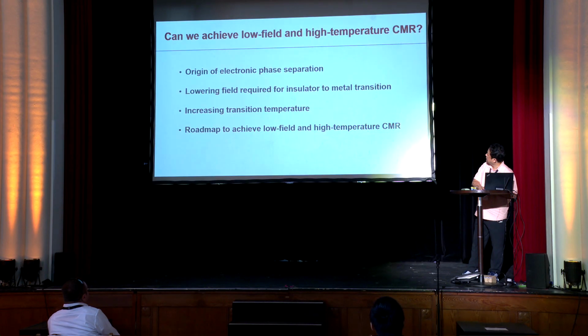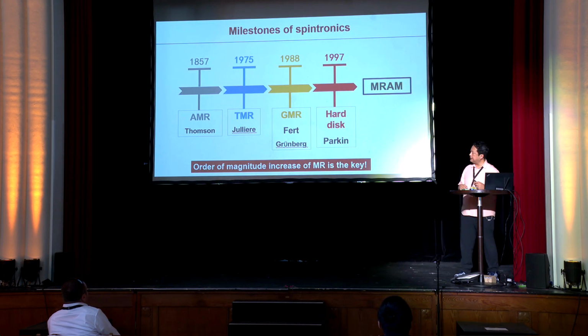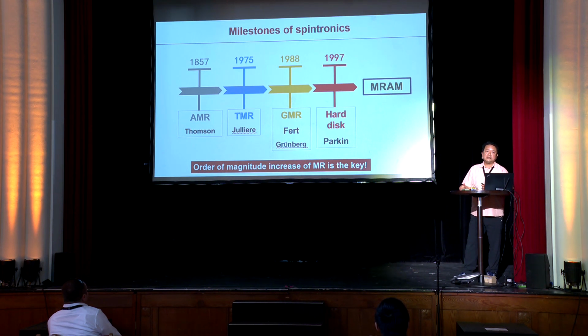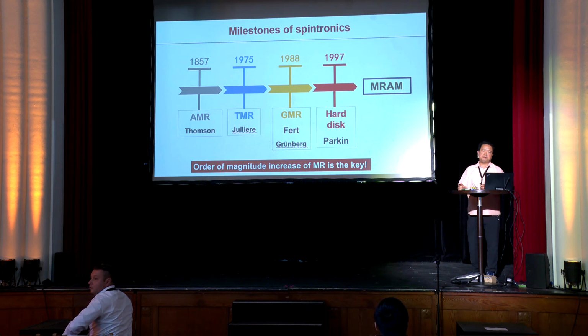So no wonder that in 1988 there was this huge wave generated by Albert Fert and Peter Grünberg, when they reported independently in PRB and PRL the observation of GMR in multilayers of ferromagnetic metals and non-magnetic metals. You have this much larger, an order of magnitude higher, magnetic resistance. Later, with the invention of the spin valve effect by Stuart Parkin, finally in 1997, IBM made the real device, in all hard disks that read based on GMR.